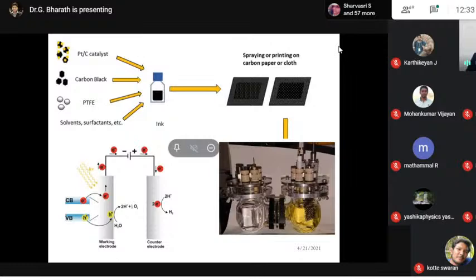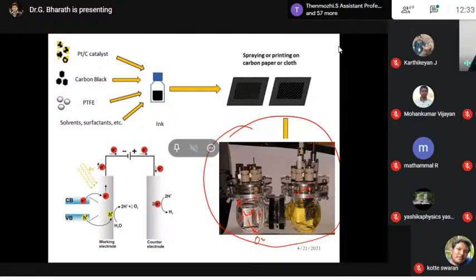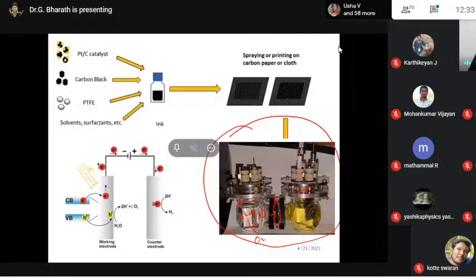Once we prepare this material, how can we fabricate the electrodes? This is the complete photoelectrochemical cell. Here this is the cathodic part, and this is the anodic part. In the anodic part, this is water splitting: H2O is split, producing O2 and H plus ions. These H plus ions easily migrate here. Here we fix a proton exchange membrane, which only allows protons. So H plus ions easily pass through this membrane and reach this chamber, which is the CO2 reduction chamber. This is the photocathode.